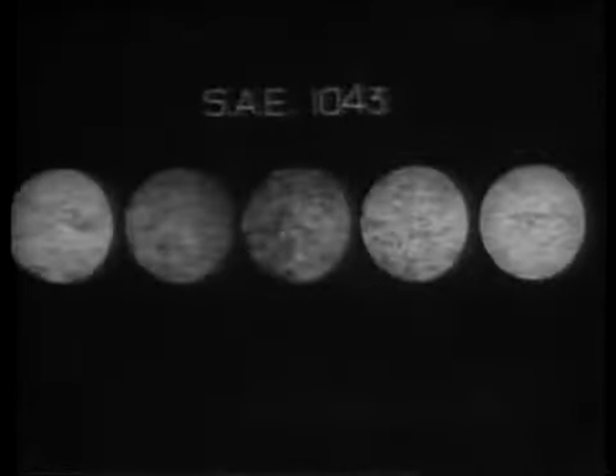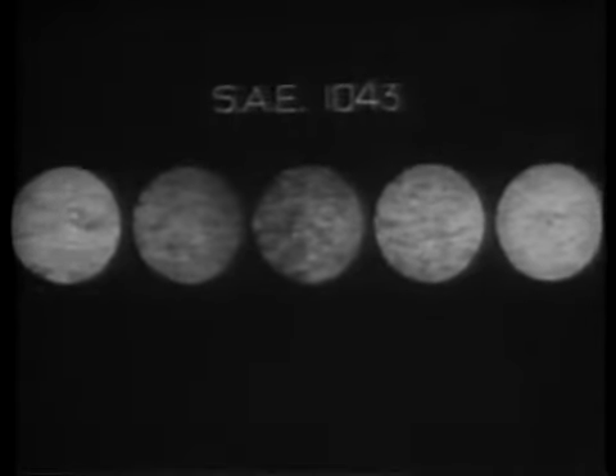Here are 5 micrographs of an SAE 1043 steel, which show its structure after tempering at progressively higher temperatures. In each stage pictured here, the steel is tougher than in the previous one. The first micrograph is of the fully hardened steel. It shows the typical martensitic structure of plain carbon steel at maximum hardness. The steel's Rockwell C reading, the measurement of its hardness, is very high, 60. On the other hand, its Charpy reading, the measurement of its toughness, is very low, 3.